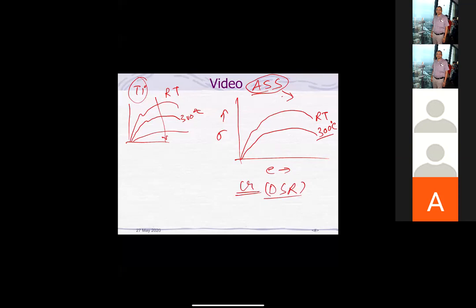In a certain temperature range, the dislocation density of the material increases suddenly. This temperature range depends upon the exact composition of the alloy, and it varies from 300 to 650 degrees centigrade. So in this range, what exactly happens, let us say at 450 degrees centigrade? If you see what happens inside the material, at a certain temperature, the mobility of chromium becomes more than the mobility of dislocation. So the dislocation is moving very peacefully, chromium comes from the back and bangs it, and this divides the dislocation into many parts. Suddenly there is an increase in the dislocation density.